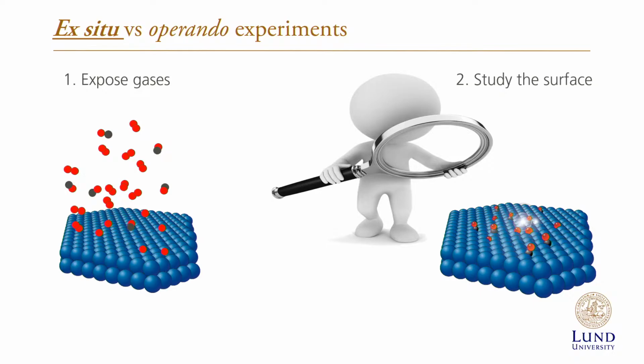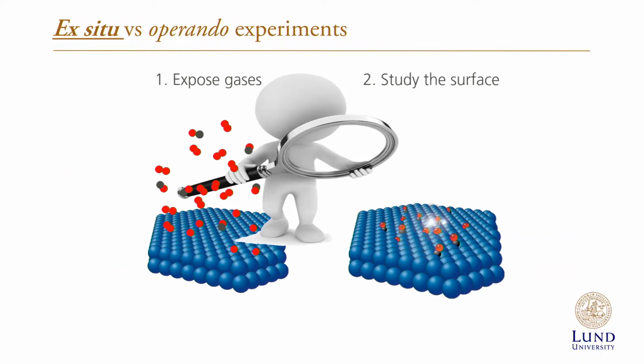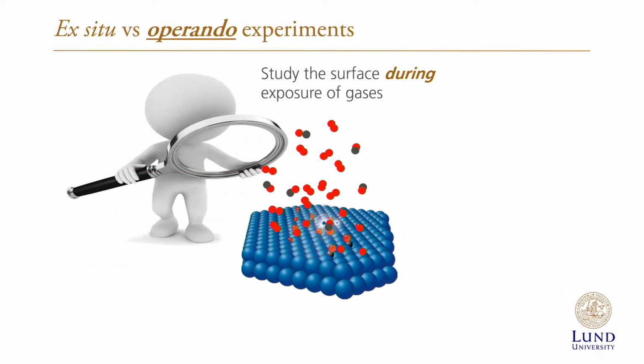Usually when you perform experiments in your home lab, you have your catalyst, you expose it to different gases, and then look afterwards at what it looks like, because you don't really have the tools to look in situ. But we would like to look into this process while it's actually happening, while the catalyst is active, while the interaction is going on. And that you can do at MAX IV.